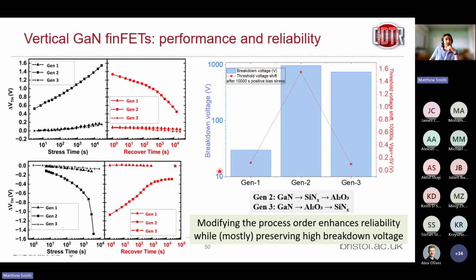So in terms of breakdown voltage, generation 1 to generation 2, we saw this huge jump, but we also saw this big jump in the threshold voltage drift. So we saw degradation in our stability. And with these generation 3 devices where we've changed the order of our process, we're essentially able to maintain the best of both. So we've got the high performance in this high breakdown voltage, and we've got this high stability now in this small threshold voltage shift under stress.